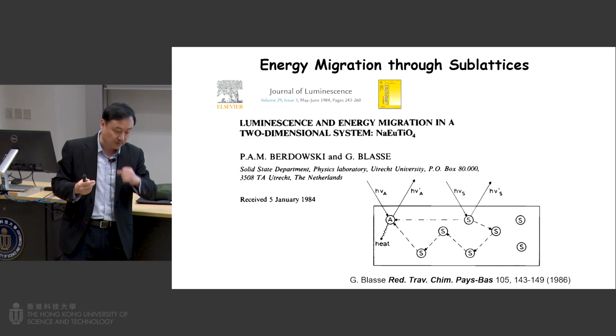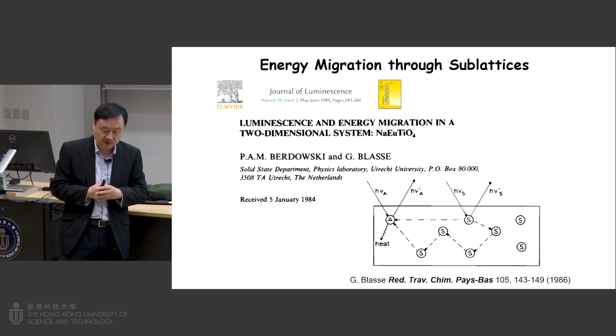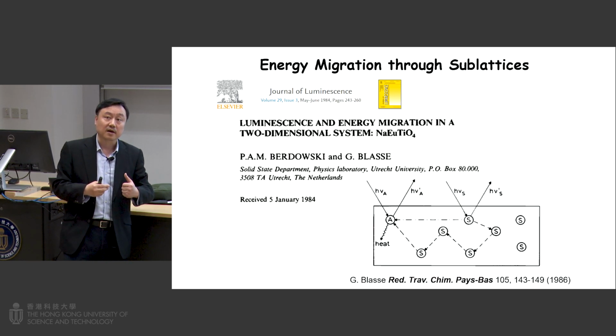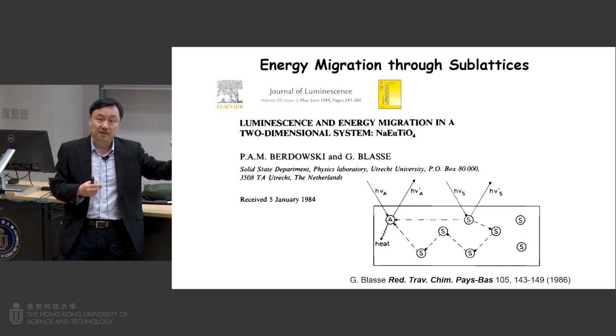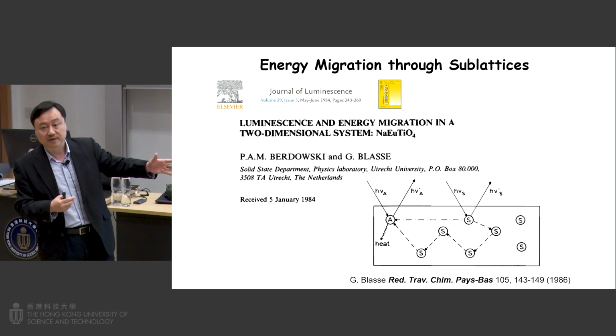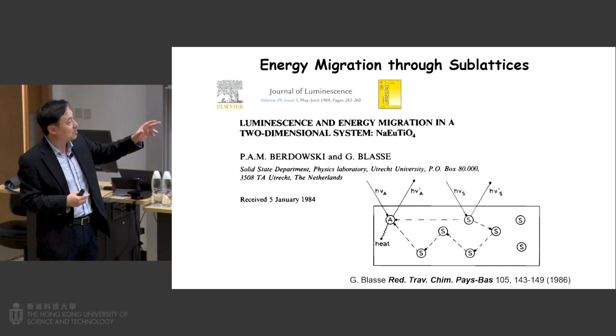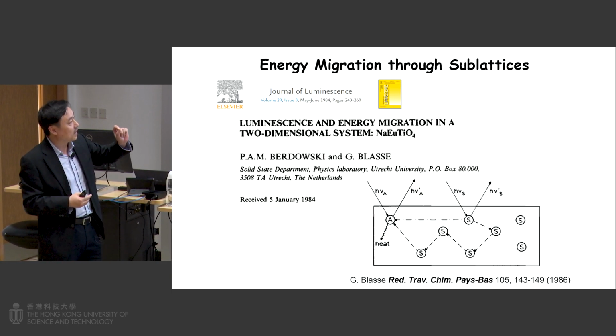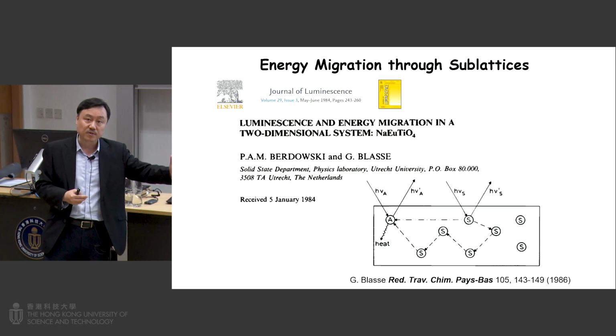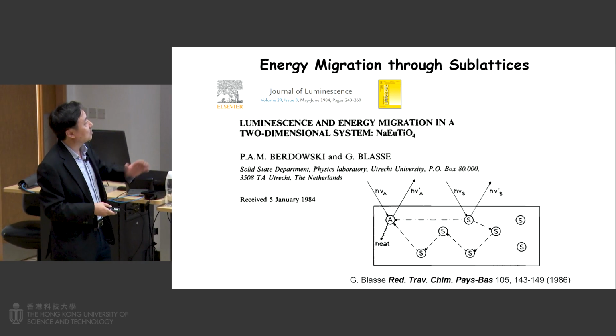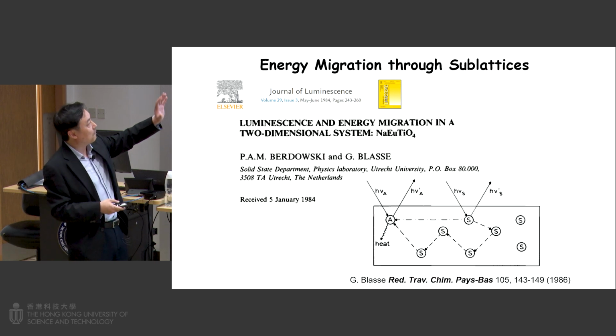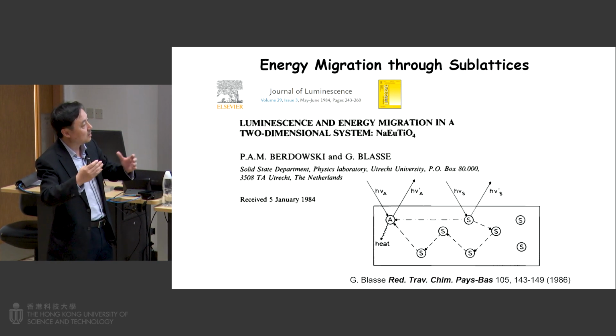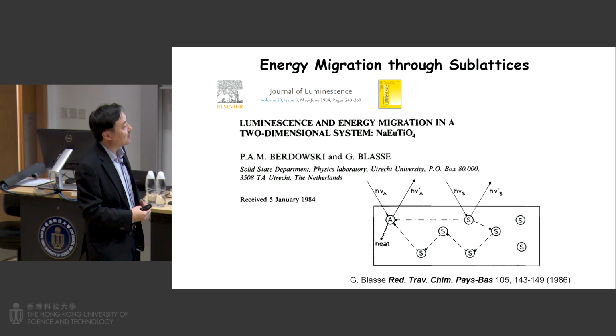I attended a presentation by a professor from National Taiwan University. He showed very impressive results with organic dyes performing this exciton migration. They showed 2 nanometers, which is already almost a record for organic molecules. But for nanoparticles, I want to showcase that using these lanthanide-doped particles, you can achieve energy migration over almost 20 nanometers.